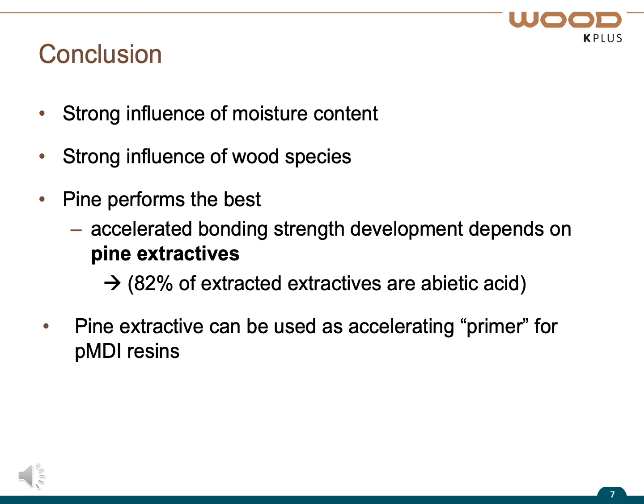To summarize my results, we could see a very strong effect of wood moisture content on the bonding performance of pMDI, as well as a significant influence of the wood species. Furthermore, pine wood performed the best, where the pine extractive seems to act as an accelerator. We furthermore analyzed the residual extractives, which consist to 82% of abietic acids. As final result, it can be concluded that these pine extractives could be perfectly used as primer to speed up the curing of pMDI.